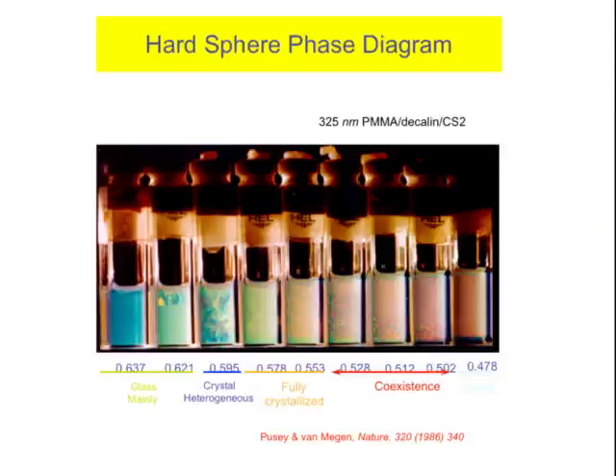You increase the volume fraction. This is about 50%, 53%. You still have some liquid. This is a coexistence region. Now you have all crystal over here. And then what he found is as you increase the density higher, you got a disordered phase, okay, which was at higher density than the crystal. That's why it's sunk to the bottom over here. And he said this is a glass phase.